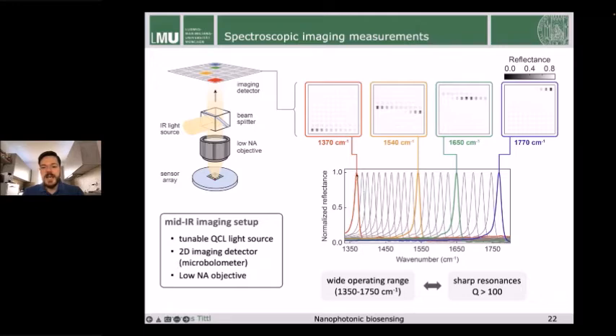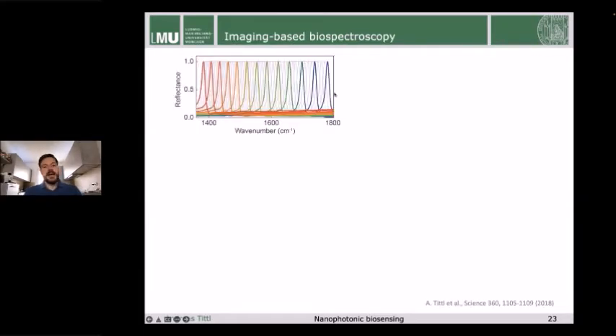And you can see we have a quite nice and wide operating range from 1350 to 1750 wave numbers in the mid-IR. So this is roughly 8 to 5.5 micron, if you prefer to think in wavelengths. And we can see that we have very sharp resonances here in the mid-infrared with quality factors above 100. So the quality factor is defined by the resonance frequency divided by the full width at half maximum. And this is more than one order of magnitude higher than the comparable plasmonic designs that I was showing you in the beginning. So now you may ask how we actually do sensing with this approach.